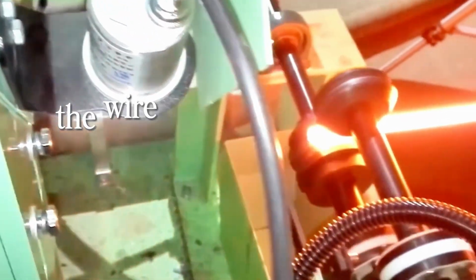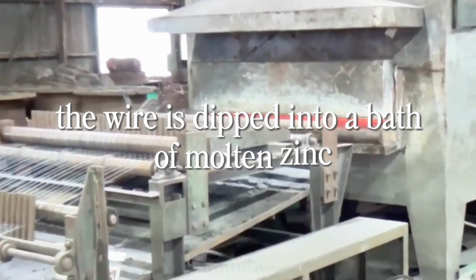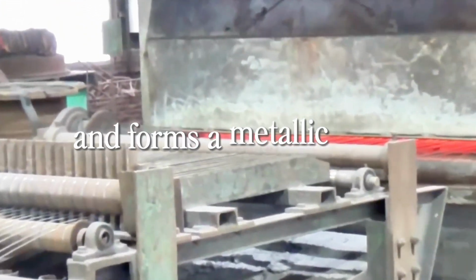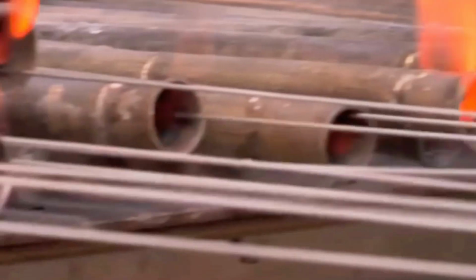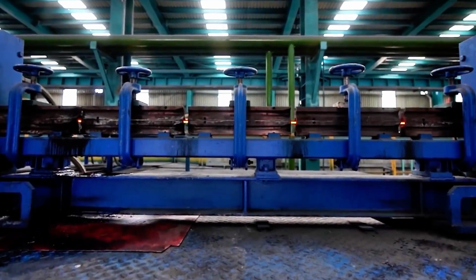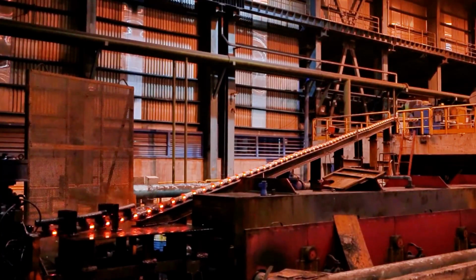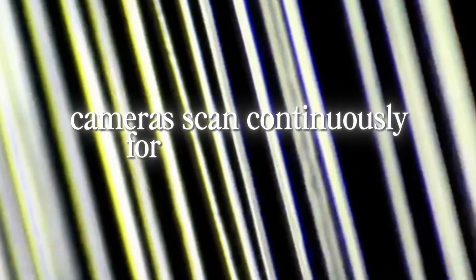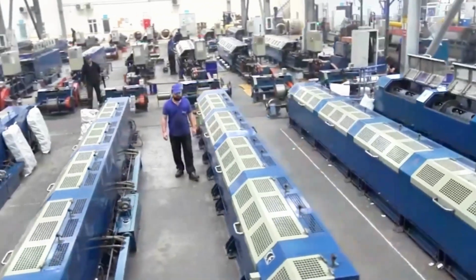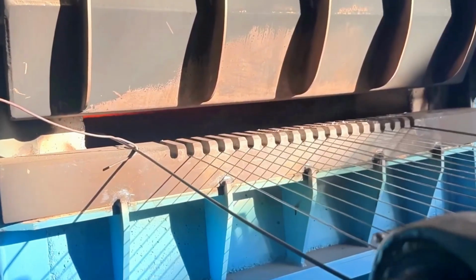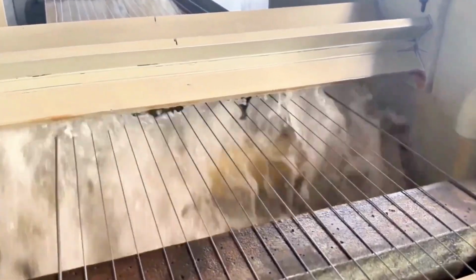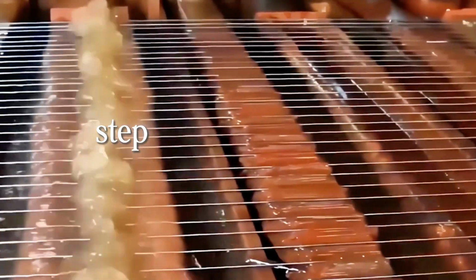In galvanizing, the wire is dipped into a bath of molten zinc, which fuses to the surface and forms a metallic armor. For cables destined for marine or industrial environments, additional polymer coatings, often in silver gray or black, add another layer of defense against salt, moisture, and chemical exposure. Every millimeter of coating is inspected. Cameras scan continuously for inconsistencies, and sensors detect any uneven thickness. Even a single air bubble trapped beneath the surface can weaken a wire meant to hold hundreds of tons. This stage ensures longevity.